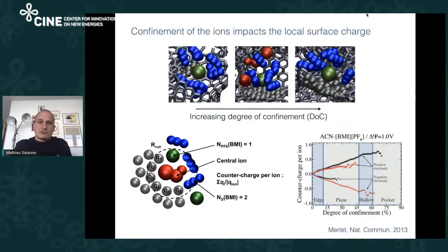Now we could also characterize a bit further the structure of the ions inside the pore, and we have introduced a quantity which we have called degree of confinement. And in fact, the difficulty here is that you have a disordered structure, so you need to have a structural definition that will tell you which kind of pore you are in. This was introduced by my former PhD student, Céline Merlet. What she proposed was to look at the solid angle around an ion, like is shown at the bottom here. When you have a few carbon atoms in this solid angle, it means that you have a small degree of confinement. In the middle, you have an example of an ion which is close to a planar surface. So that's a medium degree of confinement. And then on the right, you have an example of an ion which is very close to a kind of pocket inside the material.